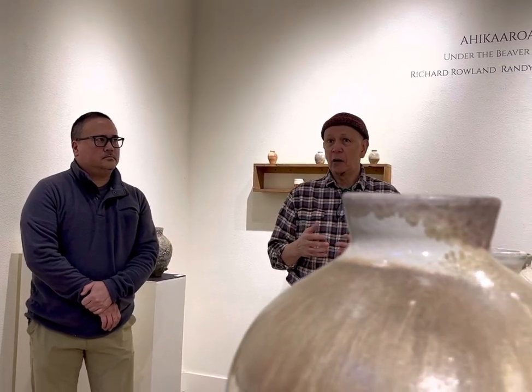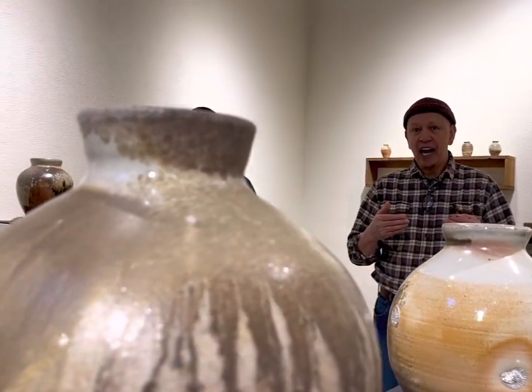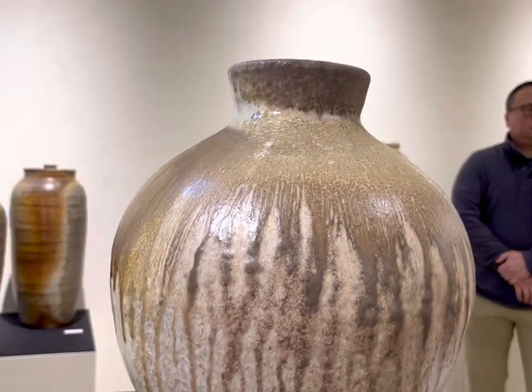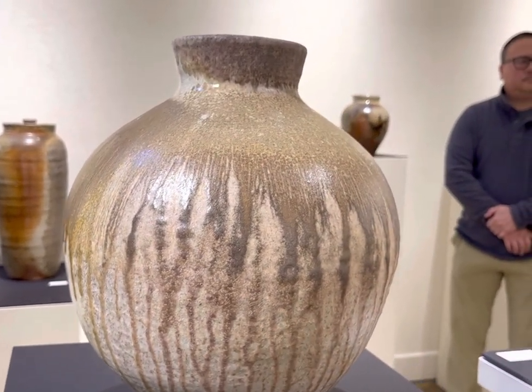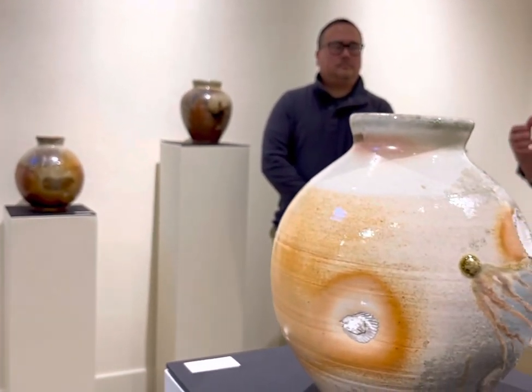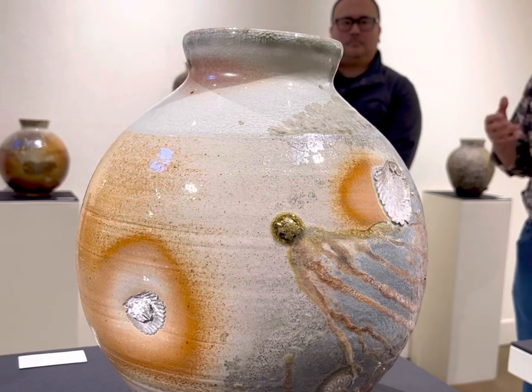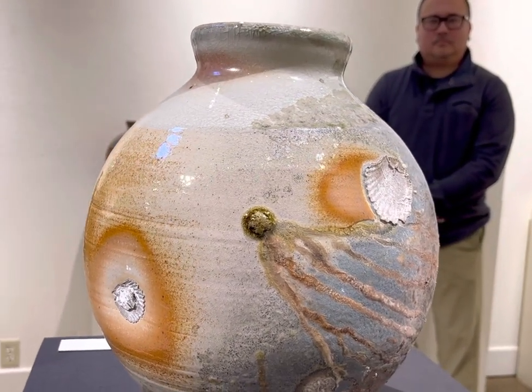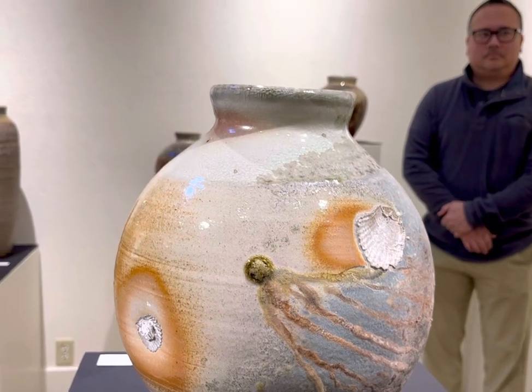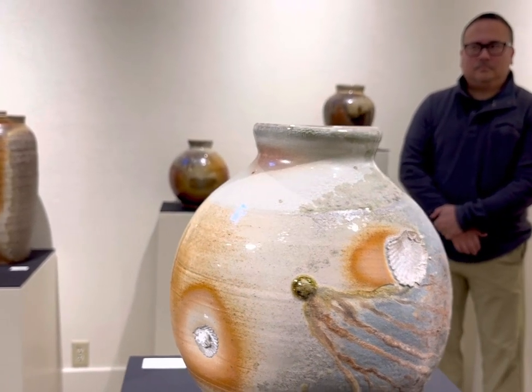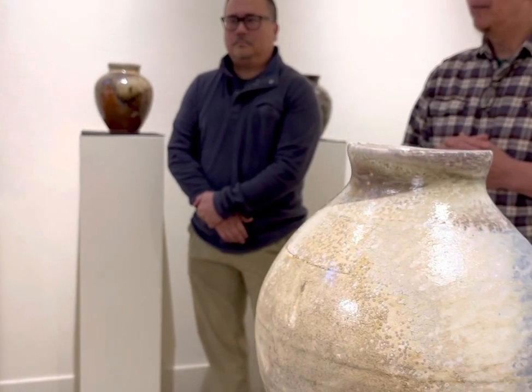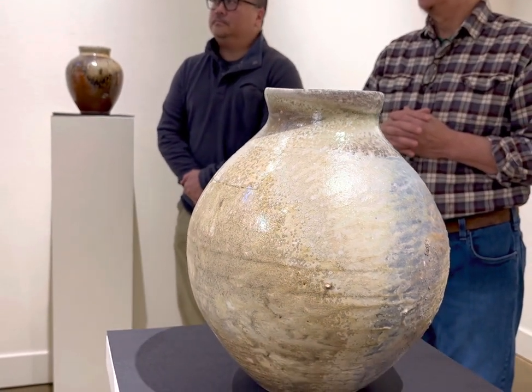And also the outcome of the type of ash on the pots is a result of a unique species like Doug fir or maple or alder. And so we can identify the type of ash and tree that we burn by looking at these pots, because Randy's been doing it for about 20 years or 30 years, and I've been doing it about 40 years. And we're finally beginning to understand what the outcome of these particular species provide to the pot. So you've done well over your 10,000 hours of mastery.